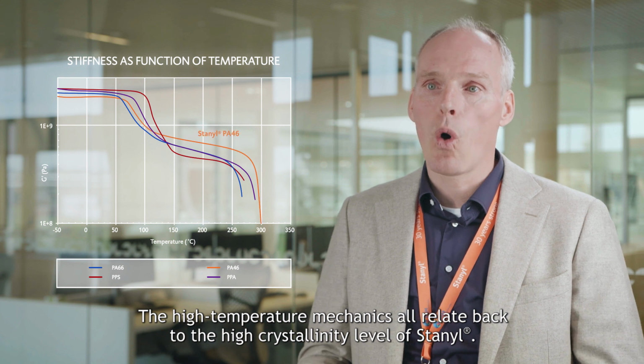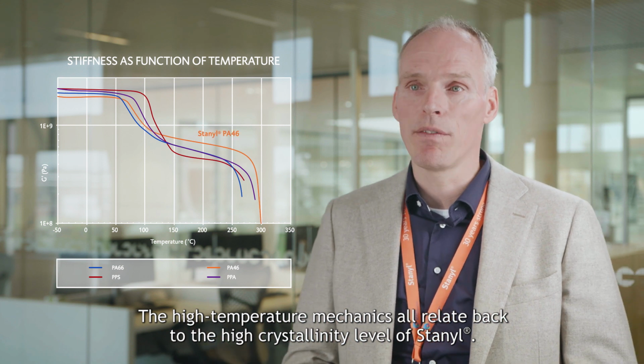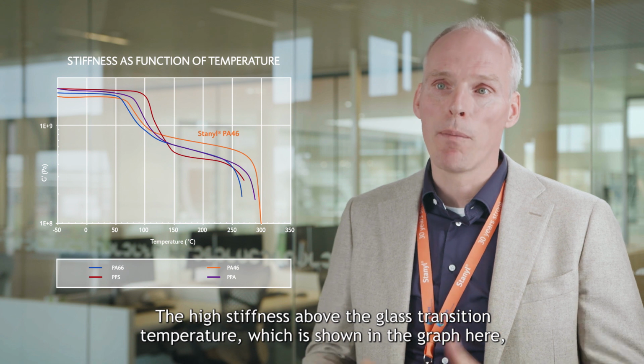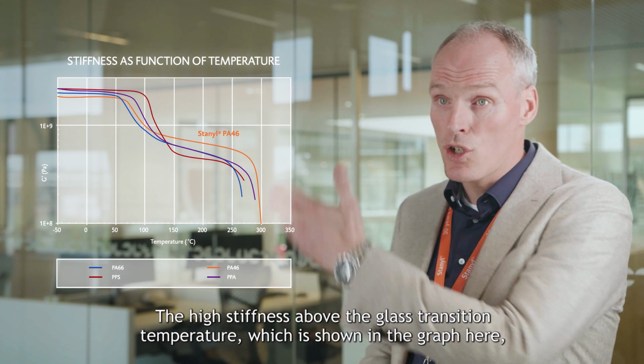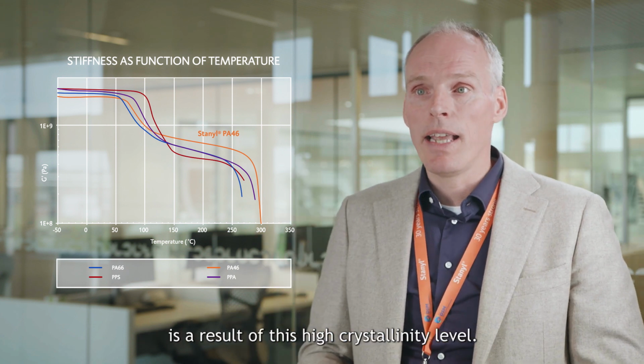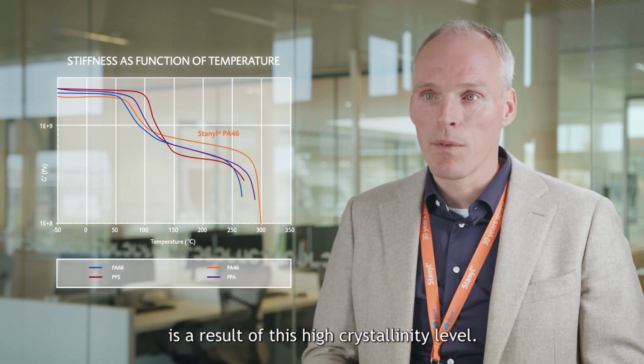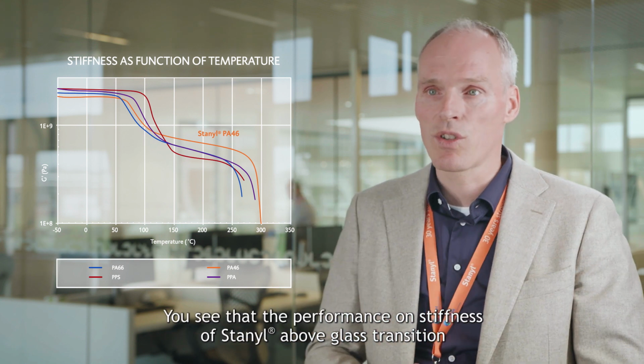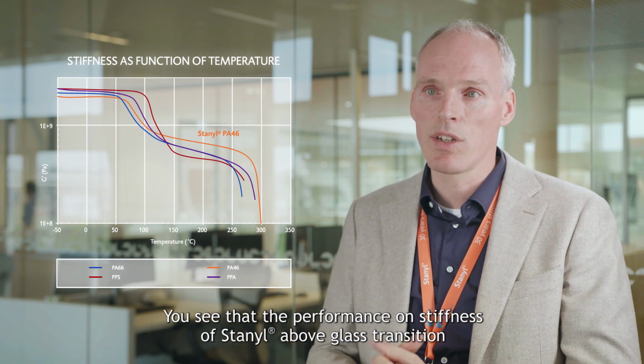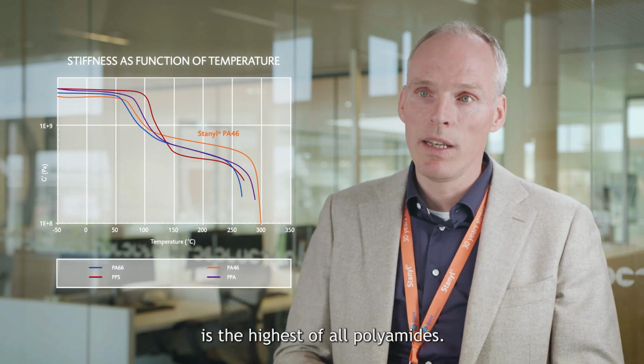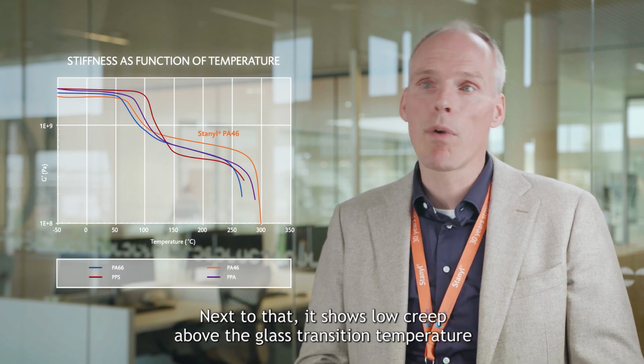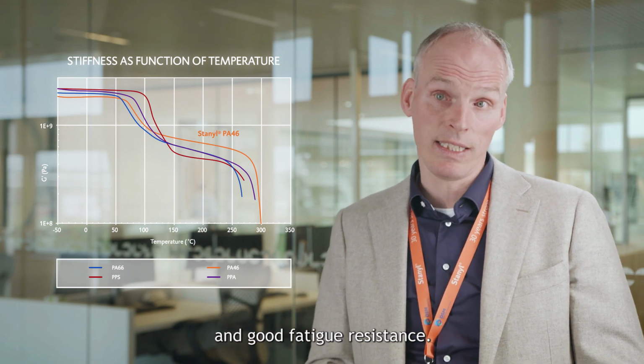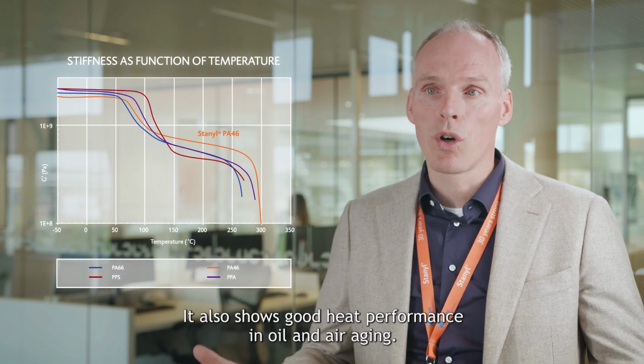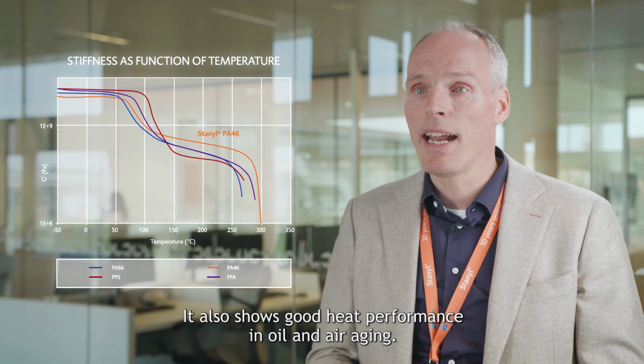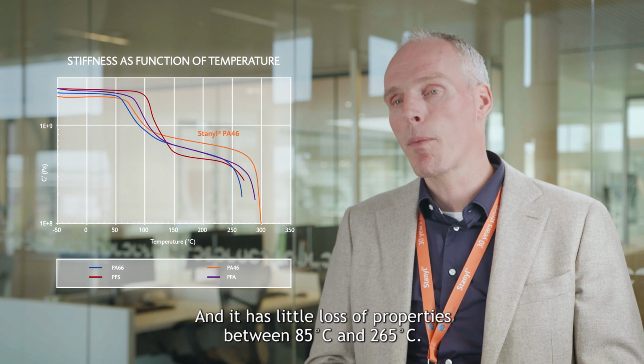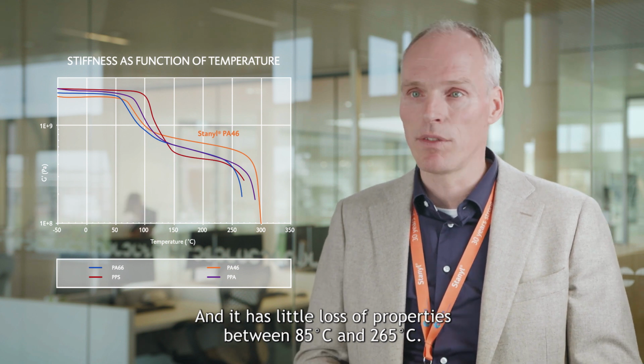The high-temperature mechanics all relate back to the high crystallinity level of Stanyl. The high stiffness above the glass transition temperature, which is shown in the graph here, is a result of this high crystallinity level. So you see that the performance on stiffness of Stanyl above glass transition is the highest of all polyamides. Next to that, it shows low creep above the glass transition temperature and good fatigue resistance. It also shows good heat performance in oil and air aging, and it has little loss of properties between 85 and 265 degrees Celsius.